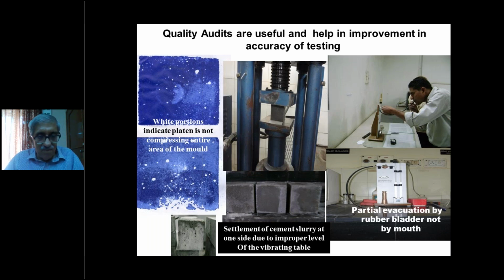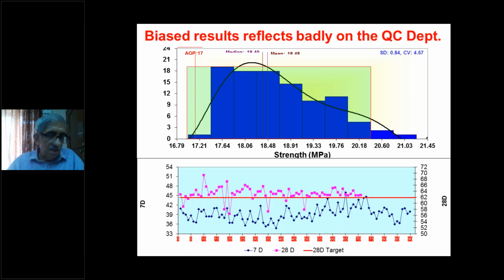Another thing important is sometimes settlement of cement slurry occurs on one of the cubes due to improper leveling and handling of the cube or of the vibrating machine. This also causes the cube to get crushed. Wherever there is slurry, it won't be able to take the correct load which you desire to carry, because aggregates are absent. So we must make sure that both these methods are done and checked for better results.